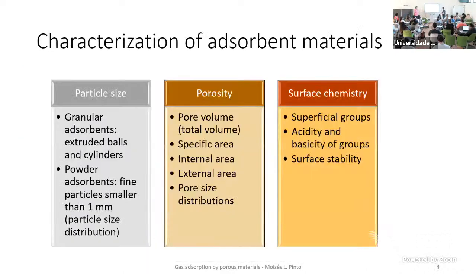So when we are characterizing adsorbent materials, so porous materials that have very high specific surface areas and quite a lot of porosity, we can characterize the materials in terms of particle size, granular adsorbents, if they are powders or beads or extrudates. We can characterize the porosity of the material. We are going to focus here on how we can characterize the porosity of the material using adsorption. And of course, there is also the surface chemistry that can play a very important role. So you have superficial groups, acidity and basicity of these groups. You have also surface stability. Okay, just to name a few. So we are going to focus here, in this middle part.